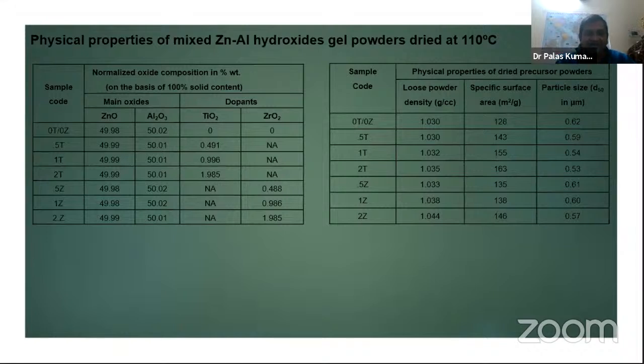The first table, the left-hand side, shows the XRF analysis, and the second one basically shows the preliminary powder characteristics. It was quite interesting that with increasing dopant concentration for both titanium and zirconia, the specific surface area gradually increases from 128 meters squared per gram to 146 for zirconia, and for titanium it is a bit higher, 163, which clearly reflects